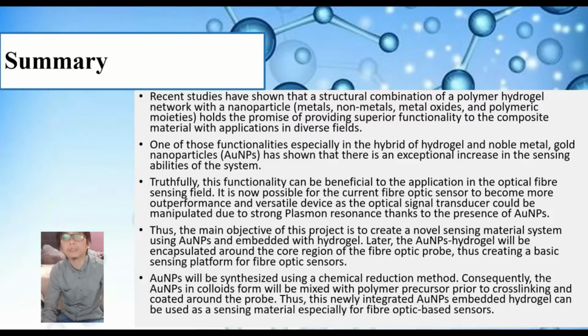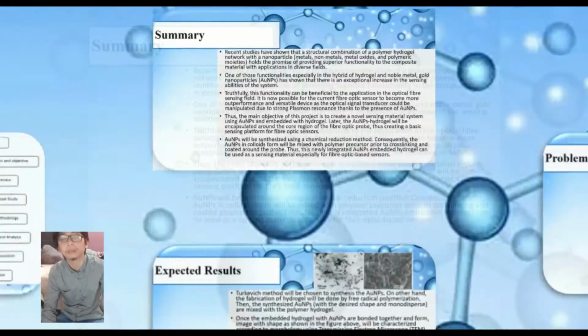Our nanoparticles will be synthesized using a chemical reduction method. Consequently, the nanoparticles in colloid form will be mixed with polymer precursor prior to cross-linking and coated around the probe. Thus, this newly integrated nanoparticle embedded hydrogel can be used as a sensing material, especially for fiber optic based sensors.